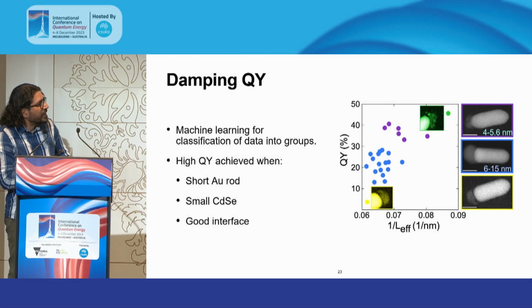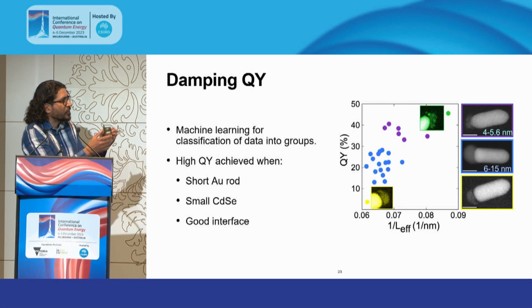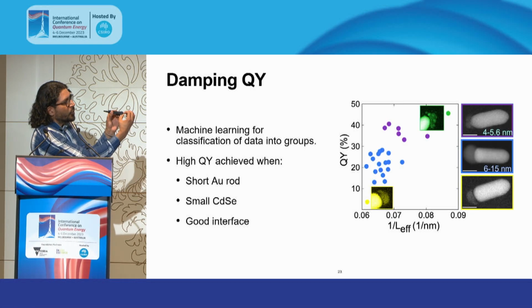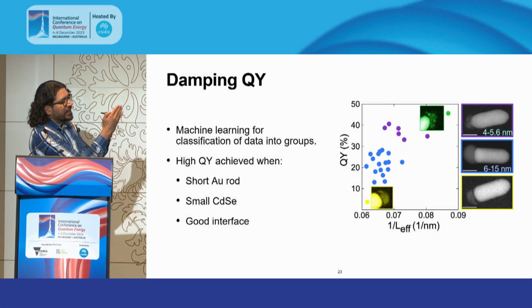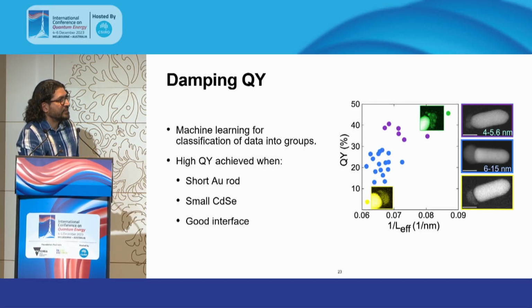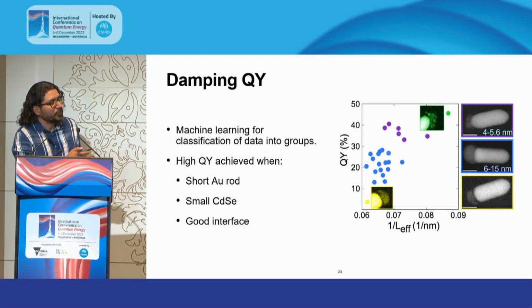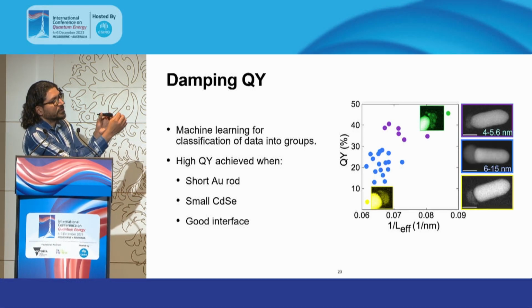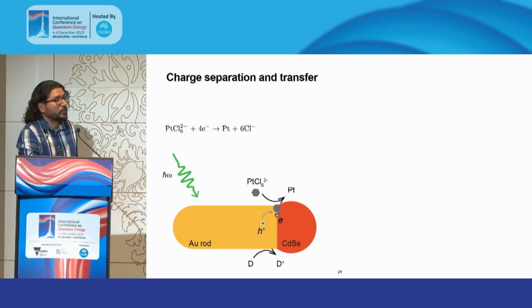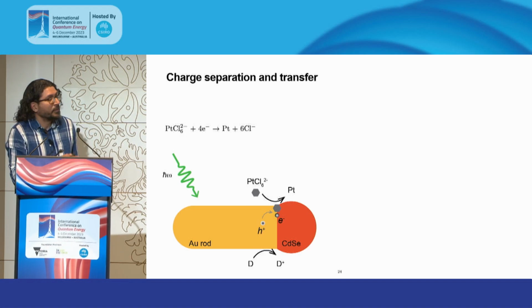And what we found is that the points here in purple are the ones that correspond to having a short gold rod, a small cadmium selenide tip, and an almost perfect interface in terms of how heteroepitaxial it is. Surprisingly, the best overall results happened whenever our chemistry failed. Instead of producing a tip, it produced a cluster of very tiny metal nanoparticles, quantum dots. As to why that is, I am not too sure.